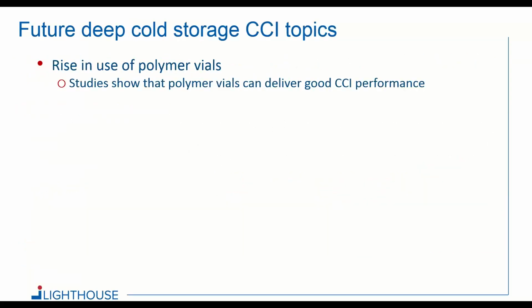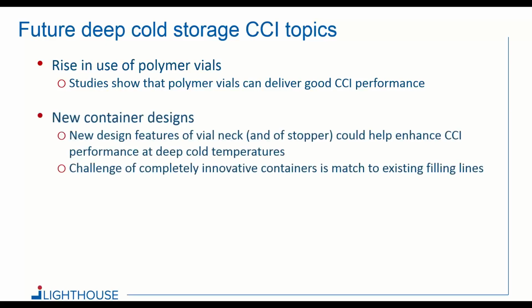I'll end with a slide on some future deep cold storage CCI topics, looking a little bit to the future. You actually currently see this now. There is a rise in the use of polymer vials for deep cold storage applications. Studies have shown that they can deliver good CCI performance, I think partly based on the fact that a polymer vial will have a similar coefficient of thermal expansion as the rubber stopper, so you might have less risk for these interference gaps. There's also been some very recent work done showing that at the polymer to polymer interface, you could get some extra sealing enhancements going on. So, as far as CCI is concerned, polymer vials are being increasingly used. You'll need to make sure that they also meet your other requirements for your formulation.